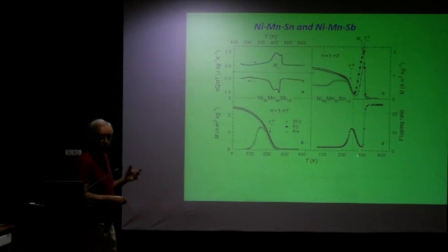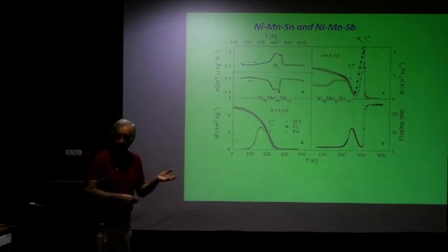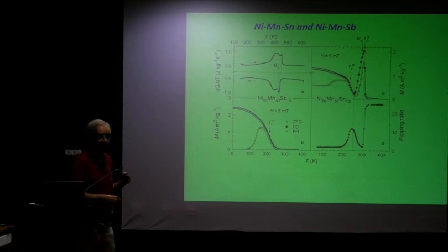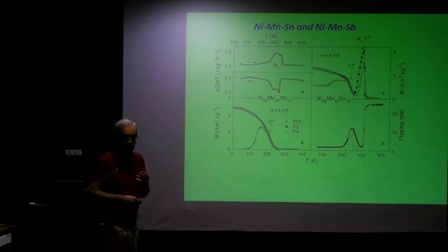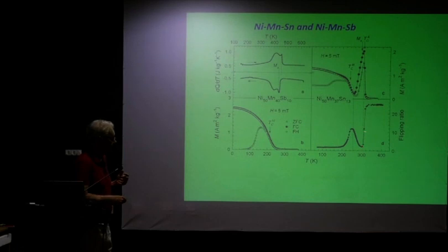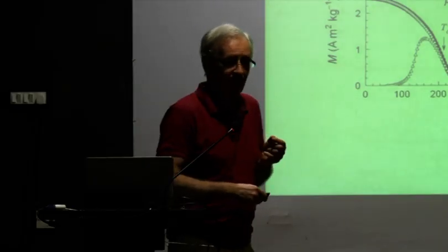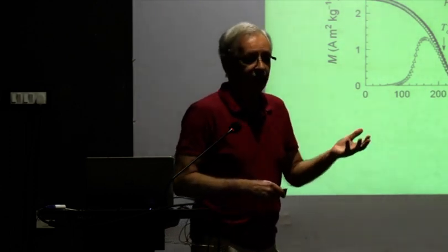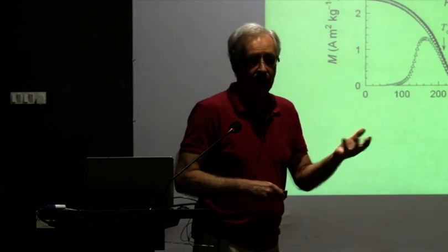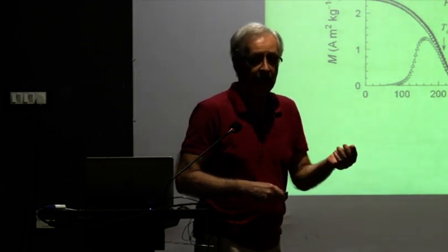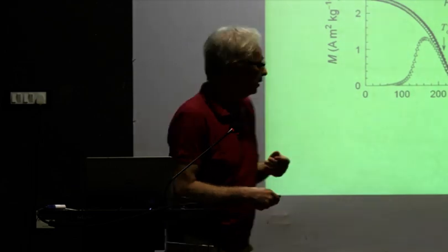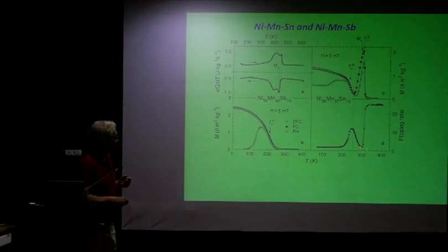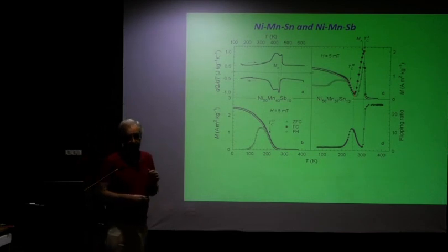And then we come here. What has happened? This is where everything became interesting in these systems. You suddenly see that the flipping ratio starts recovering. It doesn't recover to its maximum value, but it is indeed recovering. Recovering means that you have lost many of the ferromagnetic domains that you had over there. There still are some, it's still depolarizing to a certain extent, but much of the ferromagnetic domains are gone. In fact, they go and go and go, and here there is a maximum corresponding almost to the minimum in the magnetization here.